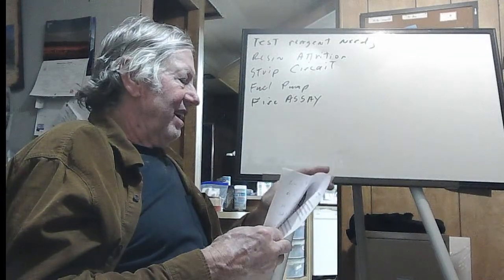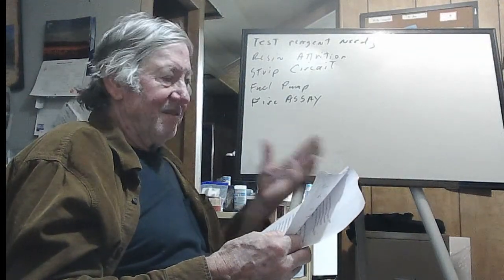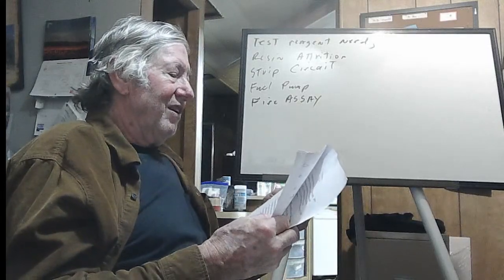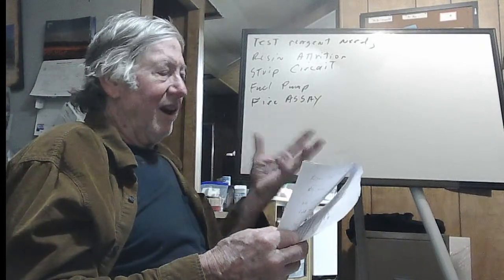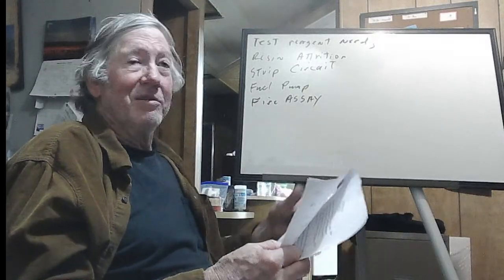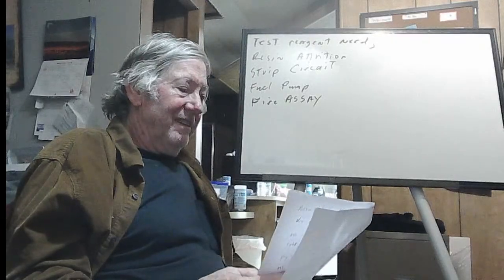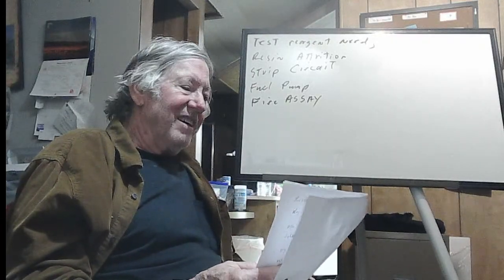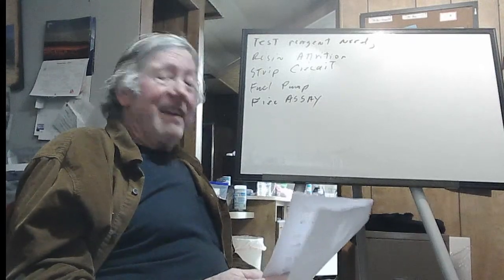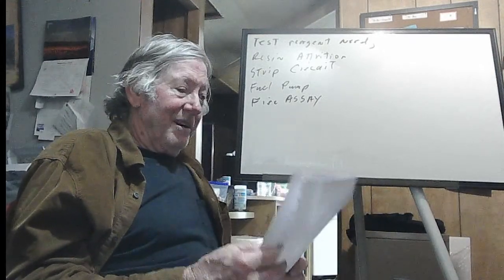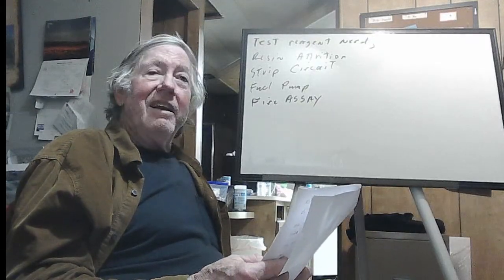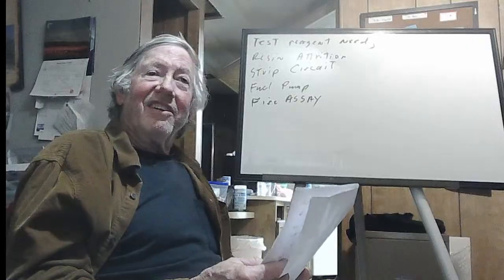We originally fire assayed wet resin, dried resin, stuff like that. And if we dried it at 70 degrees Fahrenheit, we got the same result as with directly wet resin. It's wild, but it's in these complexes, and they're kind of volatile, believe it or not. It's cyanide stuff. But anyhow, at 140 degrees Fahrenheit drying temperature, the bead was 44% smaller.